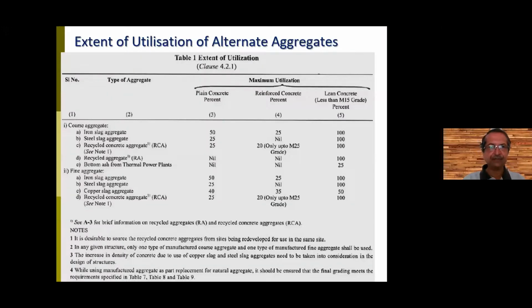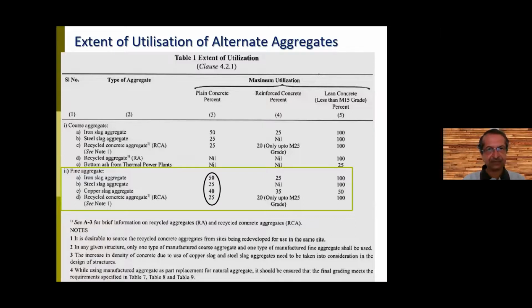Now, one thing that we must remember is, although there are restrictions which are mentioned, as I was mentioning in 383, for example, if you look at the fine aggregates, iron slag aggregates, only 50% you can use in plain concrete. Steel slag you can use 25% in plain concrete, copper slag 40%, and recycled concrete aggregate you can use 25% in plain concrete. Whereas in reinforced concrete, you can use iron slag 25%. Steel slag right now is not permitted.